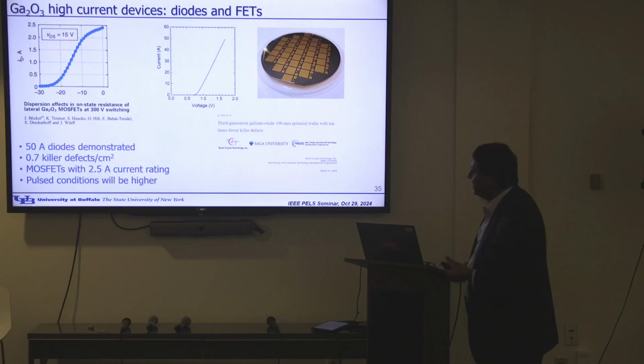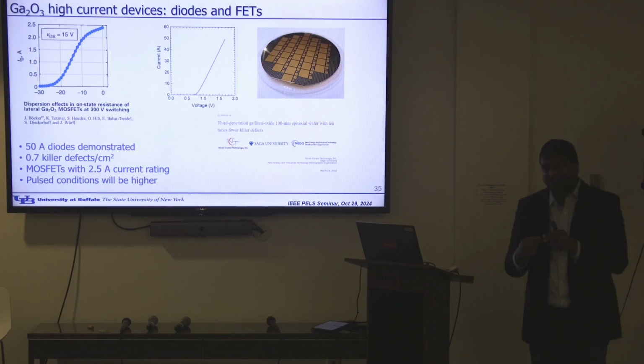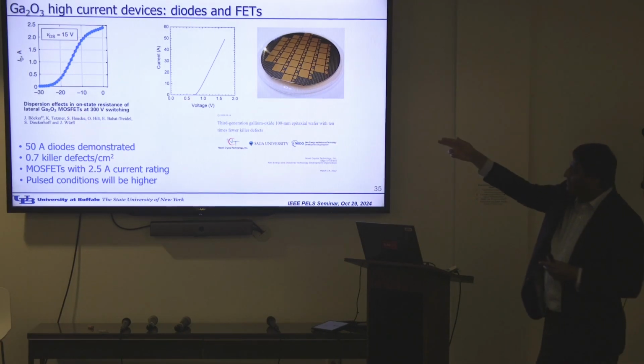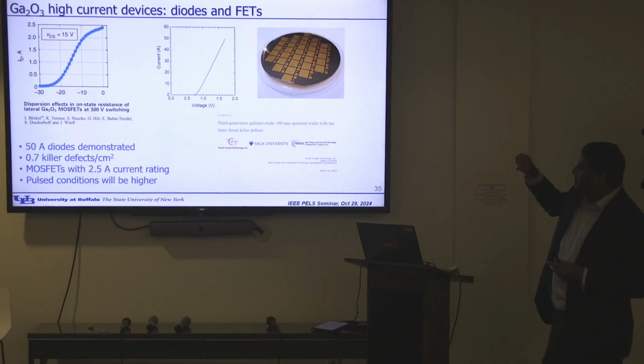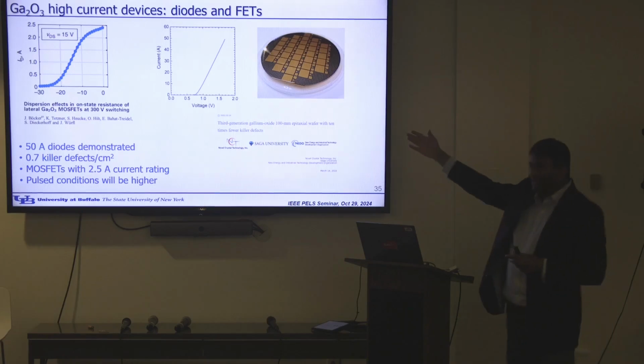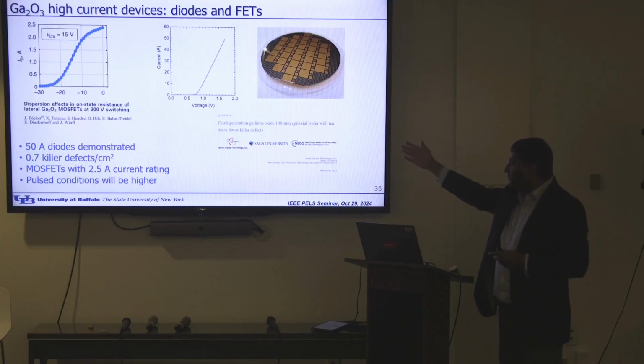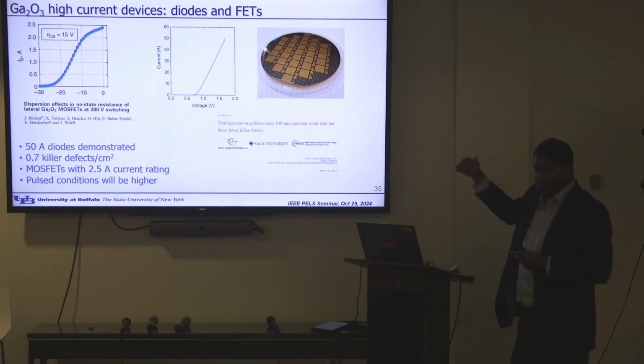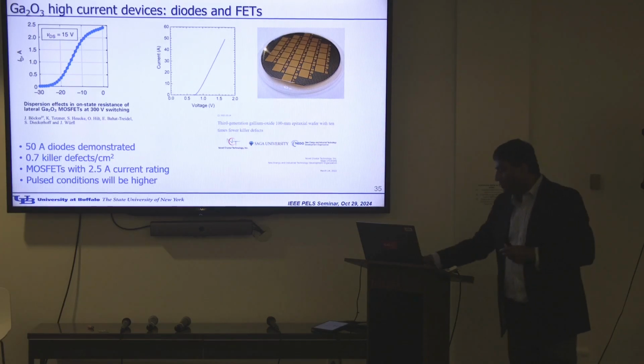2.5 amp device. Again, in our group, we still have made only small devices. We're trying to make larger ones now, so we can do some switching tests carefully. But that was the highest current device at least I could find reported for gallium oxide, right? Diodes, again, they've made rapid progress, 50 amps, 3 kilovolts, 10 kilovolts. So again, pretty impressive numbers there.